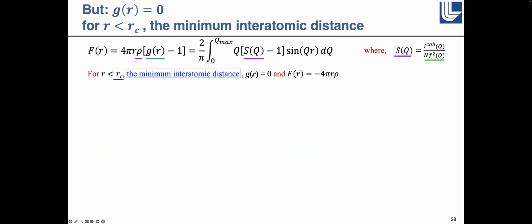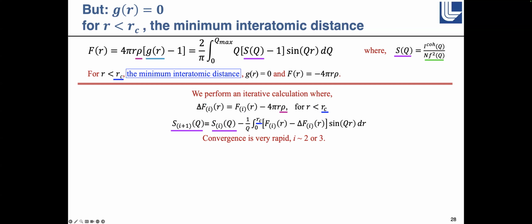So we start off with this function, and we recognize that below a critical distance, G of R has to be equal to 0. And if G of R is equal to 0, then this representation of the distribution function f of R is essentially just proportional to the negative density times R. And so we define a delta f of R as f of R minus the 4 pi r rho for R less than this critical distance. Then we can Fourier transform, so we correct this Fourier transform, and then we Fourier transform it back to get another iteration of the structure factor. And then we do this again.